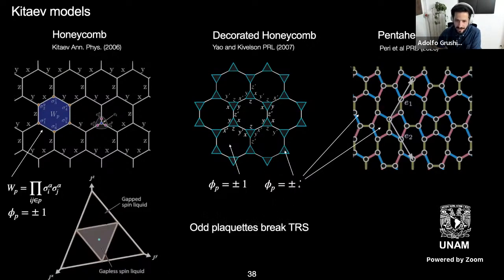And what this plaquette does, because of this i, is that the ground state no longer preserves time reversal symmetry as it did in the Kitaev honeycomb model, but actually what you get is a gapped chiral spin liquid. Now you break time reversal symmetry, and what happens is that you gap out the Dirac cones seen by these Majoranas, and you get the chiral edge modes. This was already noted even by Kitaev, that if you have odd plaquettes, you'll break time reversal symmetry.